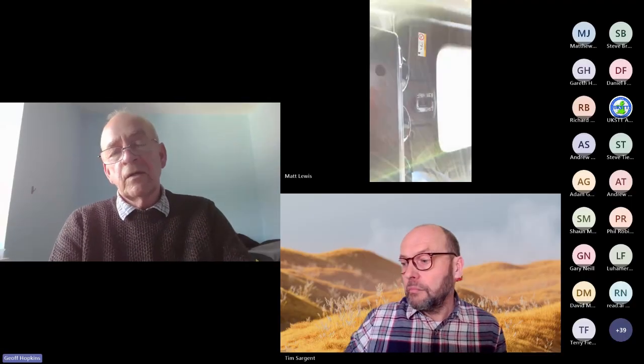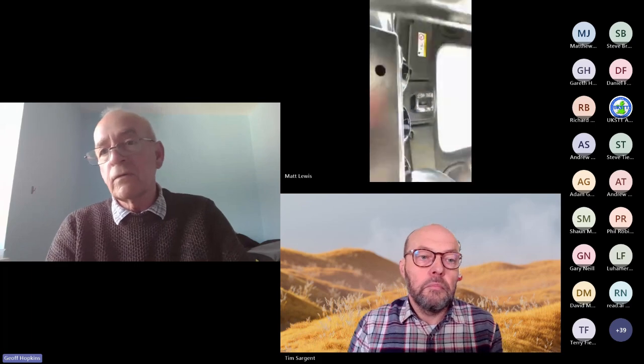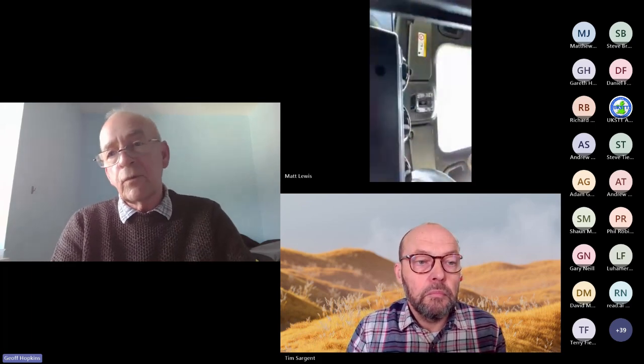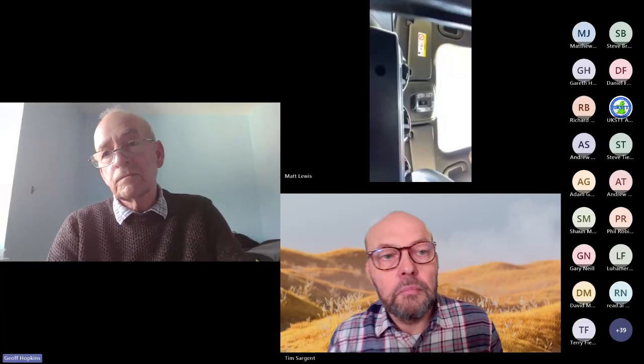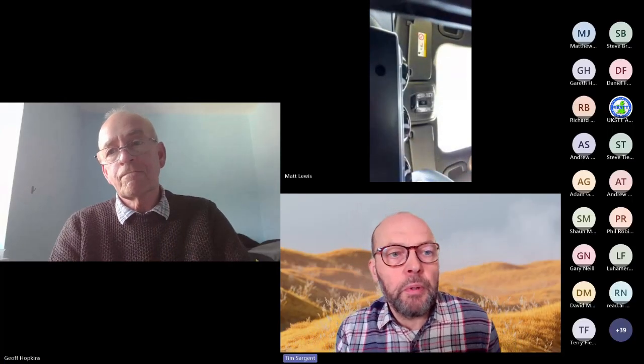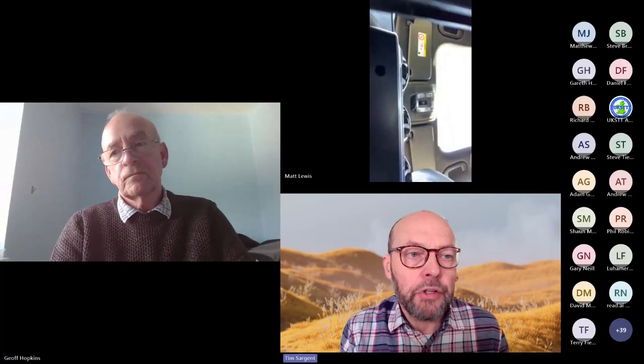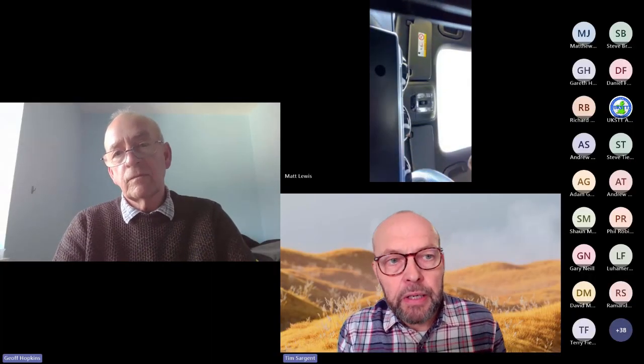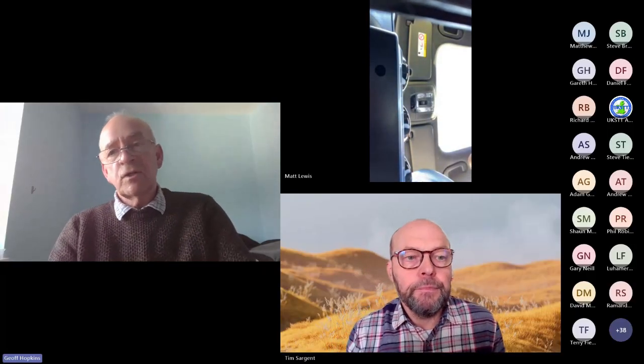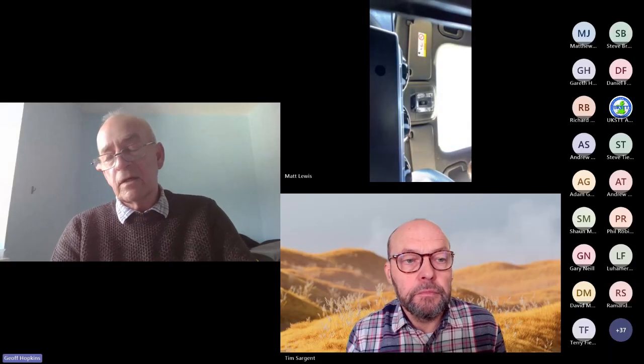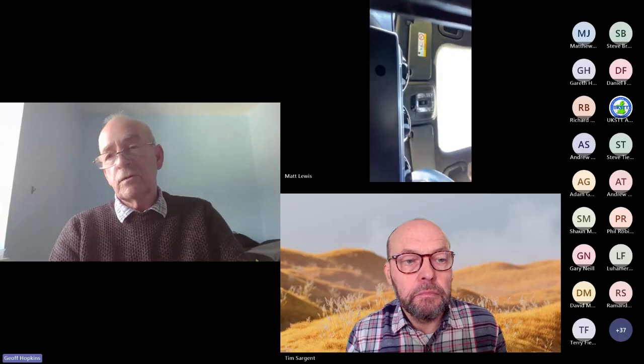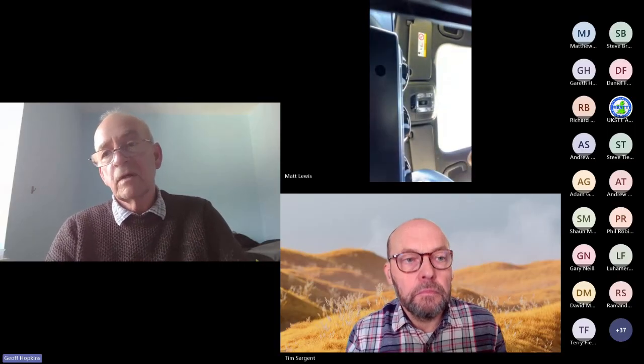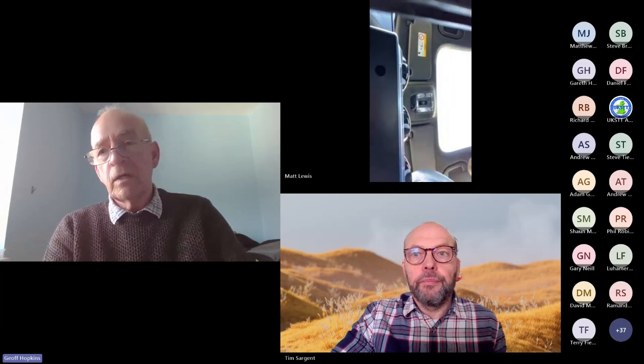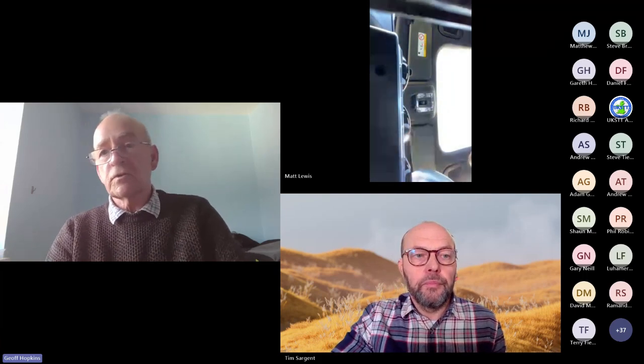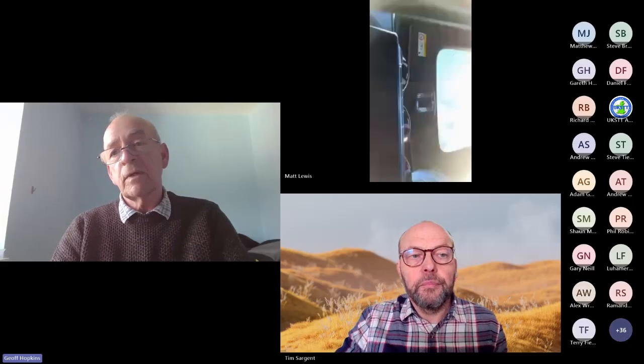Generally, I think you'd find the quickest option is just to overline the thing from the far end again, pull it all back through and overline. That's because, just to reinforce for people less familiar, it's a thin lining in the first place anyway, so you're not actually putting that thicker a lining on. You could overline a semi-structural lining if you had a 3mm lining, for instance. You could overline that again up to 6mm quite happily. So one part of it would be more semi-structural than the second half of it, which would just be back at 3mm.